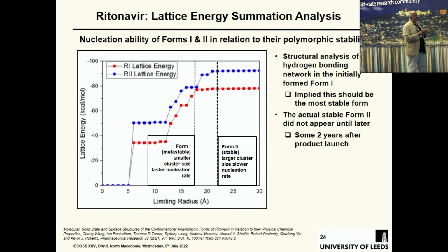So another thing you can do is you can start to look at how that molecular structure assembles by doing lattice energy calculations as a function of the limiting radius of your sphere. And you can see that, this is, if you like, the lattice energy of form 2, and the lattice energy of form 1. This is obviously more stable when you get there, but form 1 gets there first. So form 1 gets to its lattice energy at a much smaller radius.